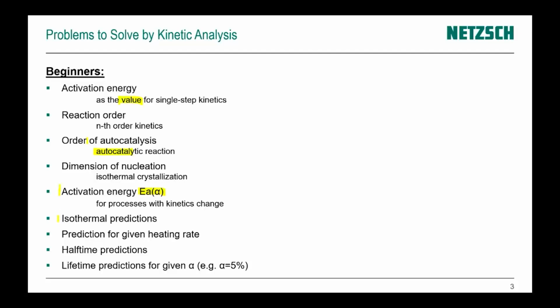The simplest case: isothermal predictions for a given heating rate, half-time predictions, so predictions of half of the reaction, or maybe lifetime predictions for a given value of alpha. For example, for decomposition of polymers, normally we speak about 5% of conversion. So if during decomposition the polymer has less than 5% of conversion, then usually it is more or less stable and can be used for the future.